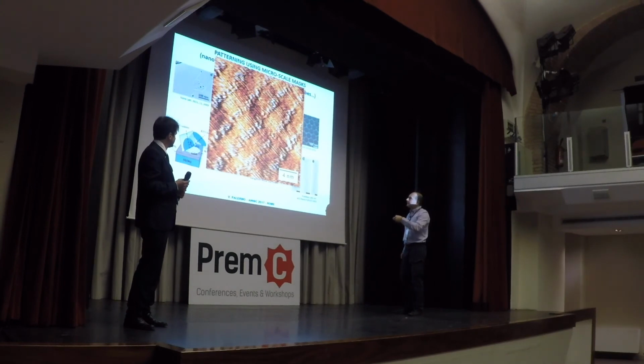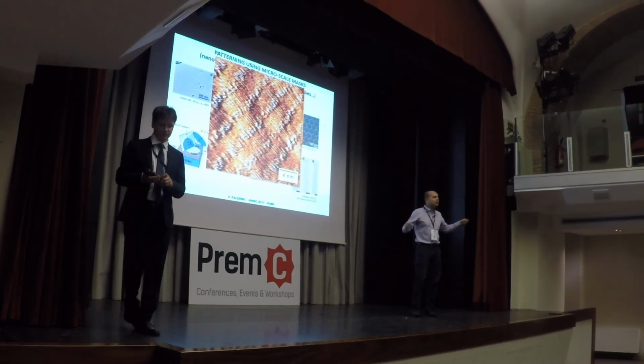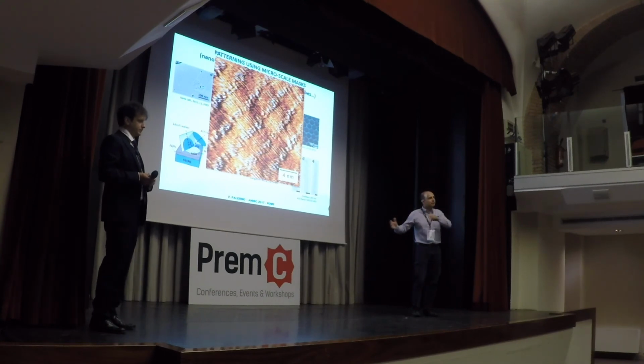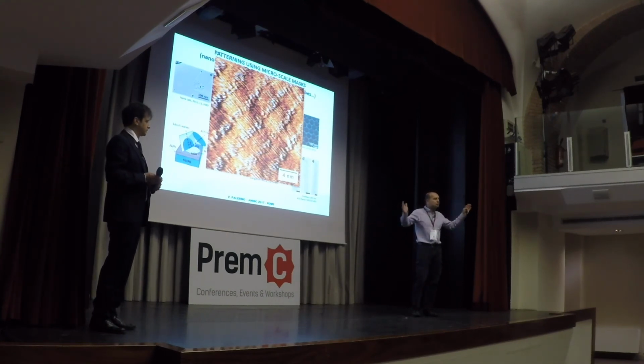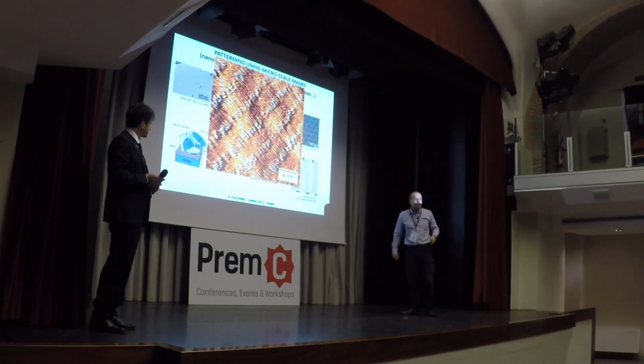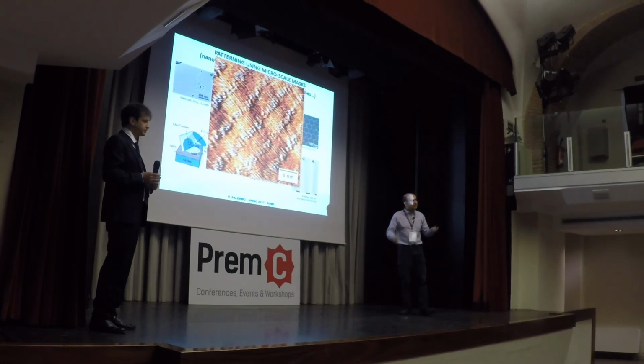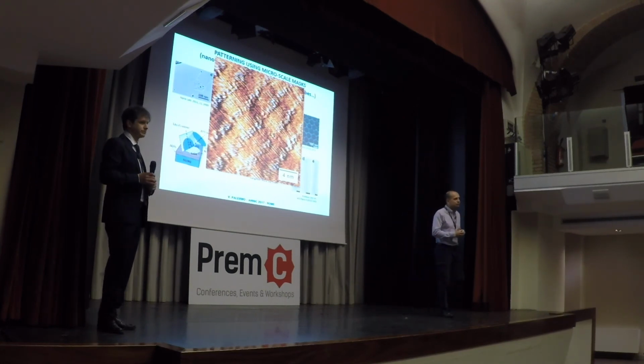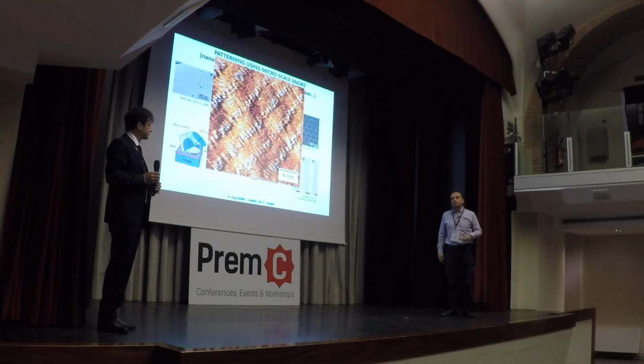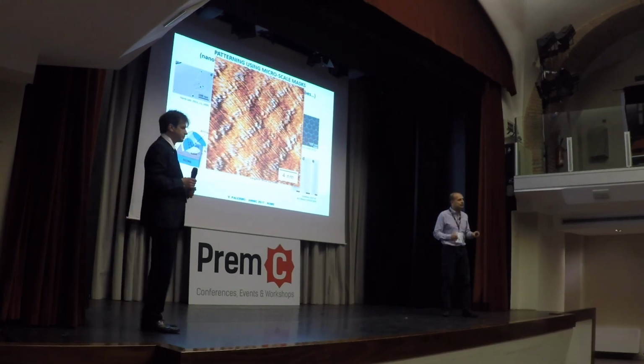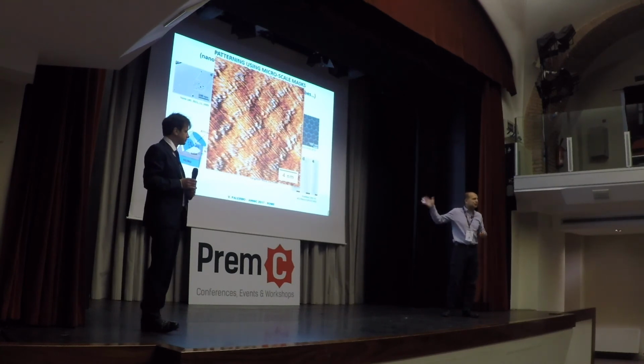And the most interesting thing is that the periodicity, so the band gap of these nanoribbons, will depend on the molecule used. So you can use an alkyl chain that is C10, C12, C14, and everywhere you will have the same size because it's not due to some lithographic thing. The final spacing between your defects will depend on the size of your molecule, which is monodisperse, so it's really well controlled. So that's why you would like to do that. If this works perfectly, then you get a transistor based on graphene that can be used in electronics. Unfortunately, it didn't work perfectly.